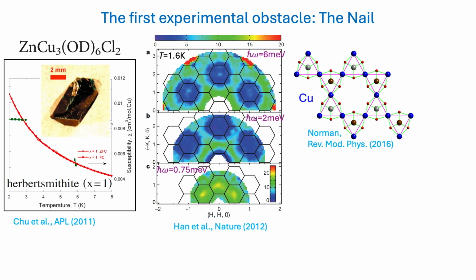Also, Young Lee's group at MIT quickly did neutron scattering. Basically, they showed this green region, which is a continuum, what is expected for a quantum spin liquid, because you're supposed to excite a pair of excitations which lead to the continuum excitation over this space. So that was actually a very rosy picture at that time. However, it was only understood later, in 2016, when Michael Norman wrote a review article criticizing this situation, basically saying that the crystal itself has 15% of copper sitting on the zinc site. So this material has a significant amount of disorder on the atomic sites.